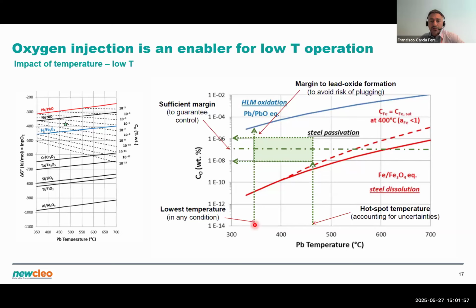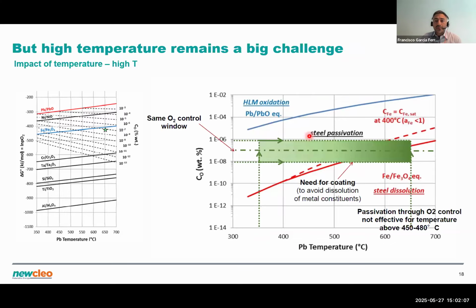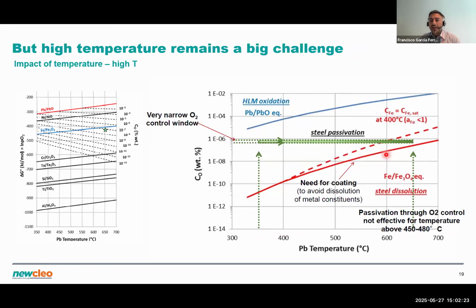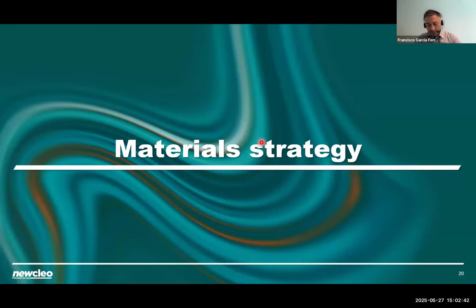And so if we consider a low temperature in our system and a high temperature, we can define a certain range where we'd like to keep our oxygen concentration. Now, if we increase the temperature in our system, which is what we would hope to do if we want to increase the efficiency of the whole reactor, we may enter a region which is not stable. And then this is not a good idea. So if we only want to rely on oxygen control to avoid the dissolution, that means we should end up with a very narrow oxygen control window. And this can become very, very tough from an engineering standpoint. So not necessarily realistic.